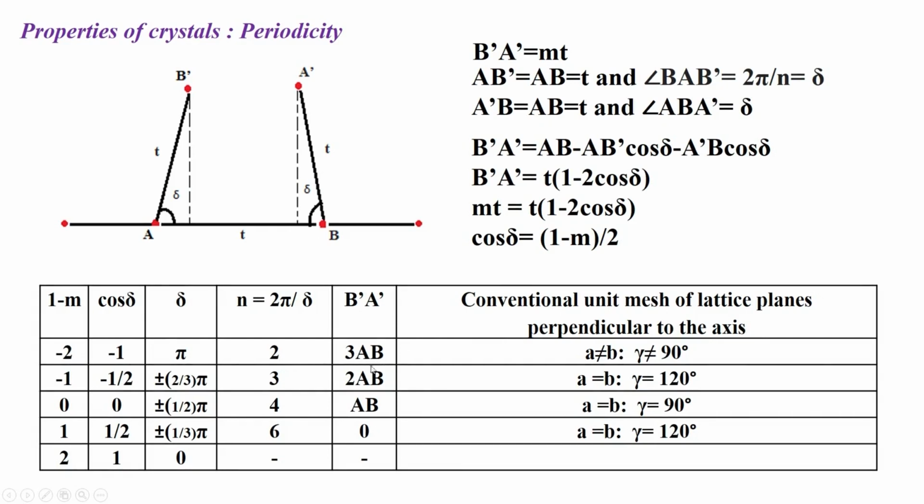Now, this defines a unit cell, because we define our unit cell in terms of these periodically repeating patterns, and this periodically repeating pattern will have to repeat in both dimensions to generate the 2-dimensional lattice. So, the basic unit cell can be defined as a quantity which has a direction A and a direction B in 2 dimensions, and the angle between them is not necessarily 90 degrees, it could be any angle. This therefore defines one possible type of conventional unit cell which we can have with a compound or a material displaying a two-fold rotation axis.